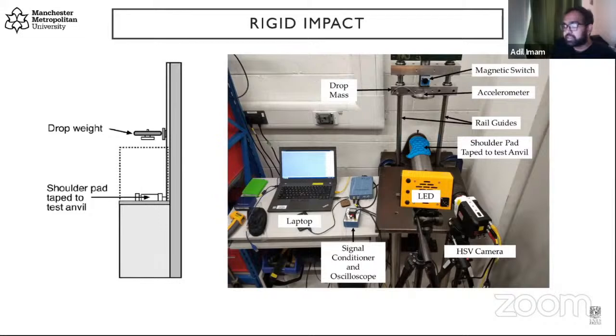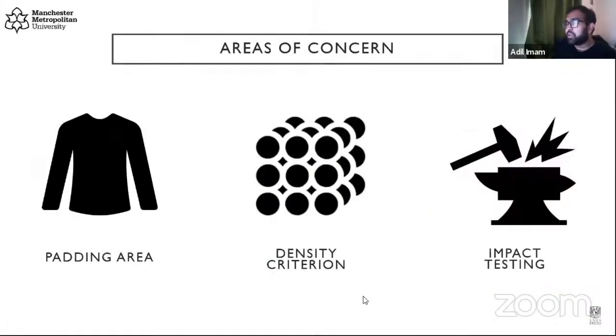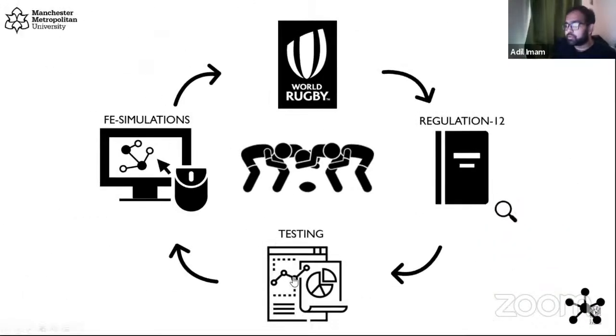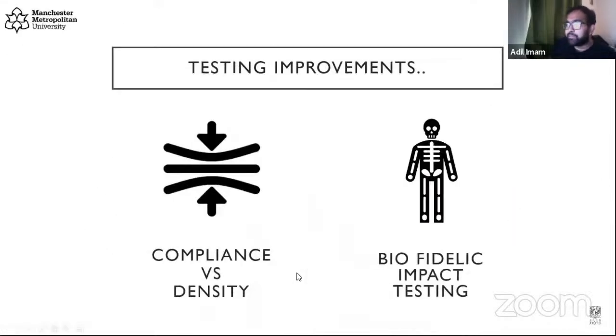And the shoulder padding that is there is only allowed to reduce risk of cuts and lacerations. Again, a flat impact between two steel objects will not replicate a cut or a laceration that may occur. So based on our findings, the area of concern, we did some testing. The first thing we looked at was compliance versus density.